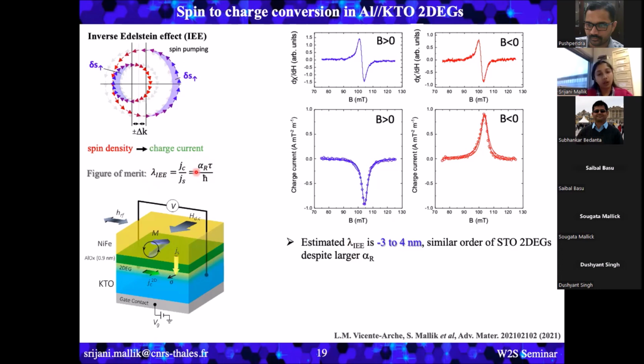And tau depends on two things. One, the mobility of the samples, and next is the effective mass of the electrons. So in case of STO 2DEGs, the effective mass is quite high, but in case of KTO, it is like one order of magnitude lower. So although we gained one order of magnitude in alpha, finally we lost a similar amount with the tau. And finally we end up with a similar order of magnitude of lambda in case of KTO 2DEGs.